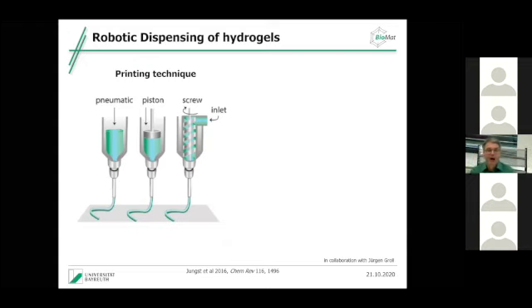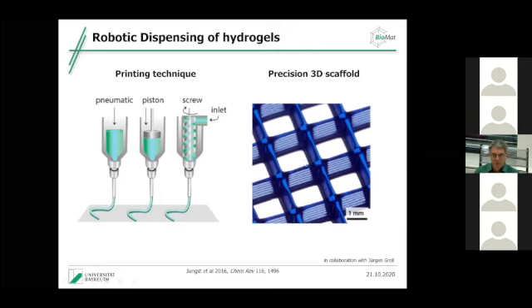And for that, we tested robotic dispensing. So what you do is you put this hydrogel in any kind of capillary, and then, even pneumatic or with a piston or with a screw, you actually press it through a needle. And if you have a good hydrogel, it starts to flow when the pressure is set on, and it immediately hardens as it comes out. So this is called the shear thinning behavior. And then you actually can make precision 3D scaffolds.